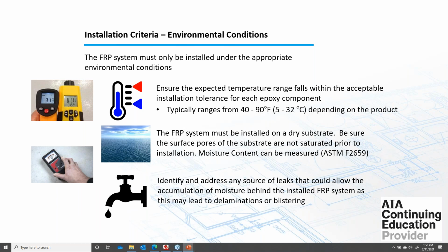The FRP system must only be installed under the appropriate environmental conditions. So first, ensure that the expected temperature range falls within the acceptable installation tolerance for each epoxy component. Typically, the range is between 5 to 32 degrees Celsius, so between 40 to 90 degrees Fahrenheit.